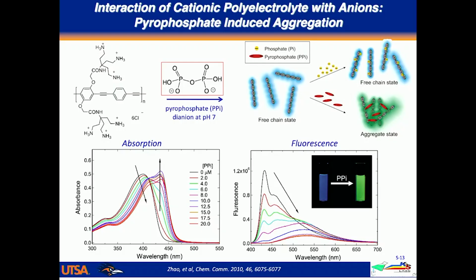But what we found quite interestingly is if you add this ion to the solution of that polymer in water, this ion is called pyrophosphate by the biologists, or sometimes abbreviated PPi. It turns out PPi induces the polymer's fluorescence to go from that blue to green color, characteristic of the aggregation. And we think that the pyrophosphate essentially has a molecular recognition and ionic interaction with these positively charged ammoniums, and it bridges at least two chains, which then collapse into an aggregate structure.